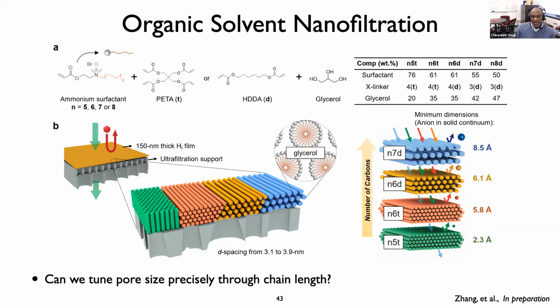And here for us, the really compelling thing is that we can change ever so slightly the structure of the molecule that's used to make the mesophase that provides the membrane, or we can change the volume fraction of that surfactant, and in so doing, change in very small increments the dimensions of the transport regulating features that are provided by that membrane. And so this is a work in progress, and that's what Yicho did.